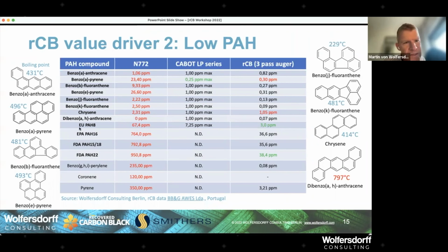In Europe, we are looking at the EU group of 8. These are the 8 PAH compounds that are listed here. Elsewhere, for example in the US, you might look at the EPA 16, the FDA 15 or 18, or the FDA 22. Then, of course, you get different numbers. Also, there are polycyclic aromatic hydrocarbons that are in none of these groups, and these are very, very high in the furnace carbon black, so that we can say the total content of PAH in furnace carbon black can go as high as 1,000 ppm, and is higher the bigger the particles are. And the 700 group of carbon black has a very big particle size.